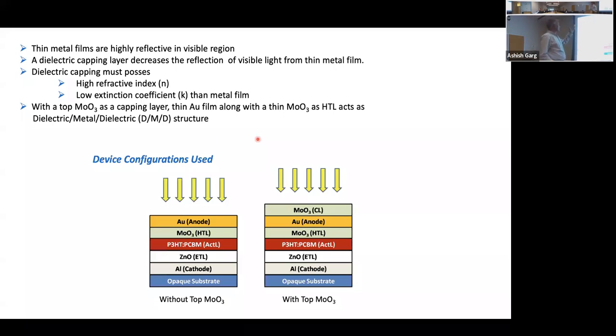One, we need to choose a dielectric capping material which reduces the reflection of visible light from the top side. It should have a high refractive index, so you bend the light more and more to increase the absorption. Secondly, you should have a low extinction coefficient of light in the thin film. If you fulfill these two characteristics, then we should be able to get a transparent electrode with more transparency. So we chose two samples.